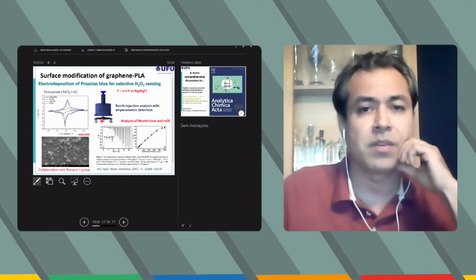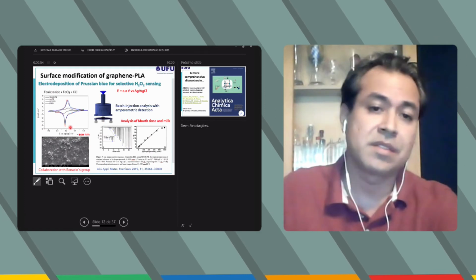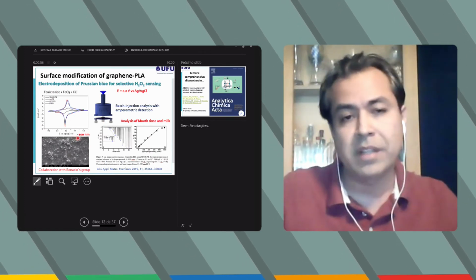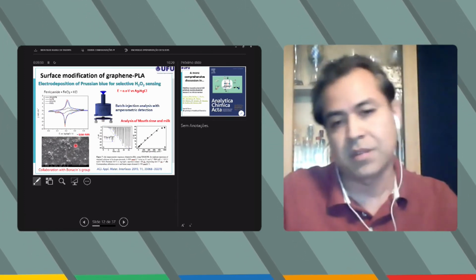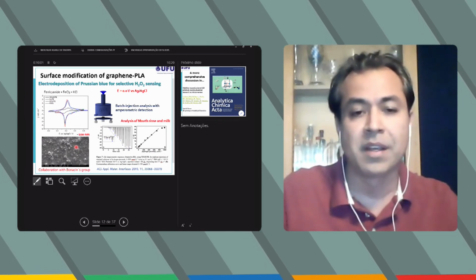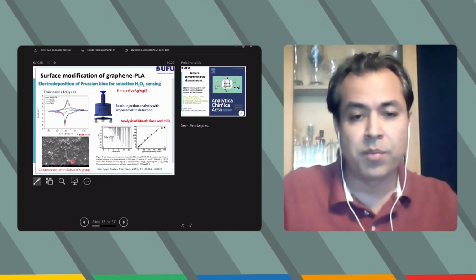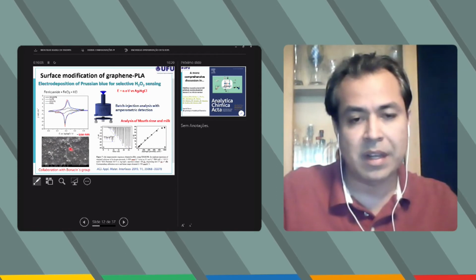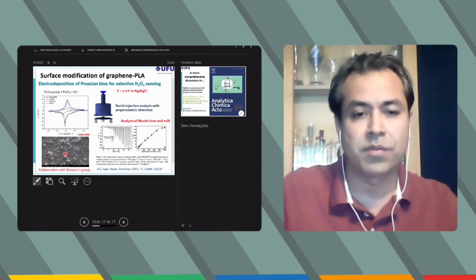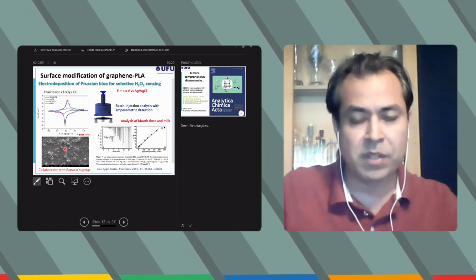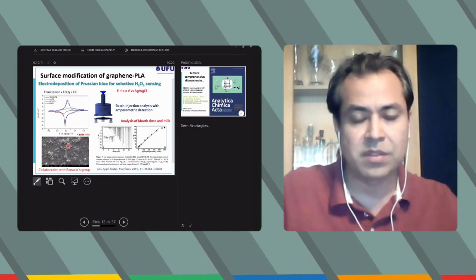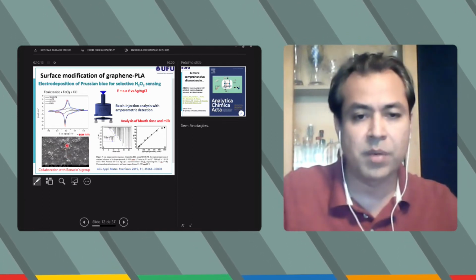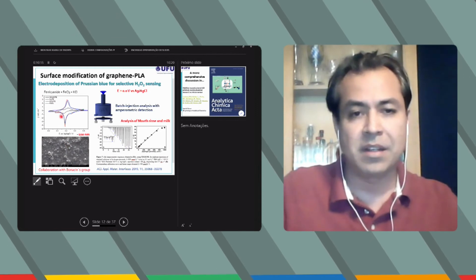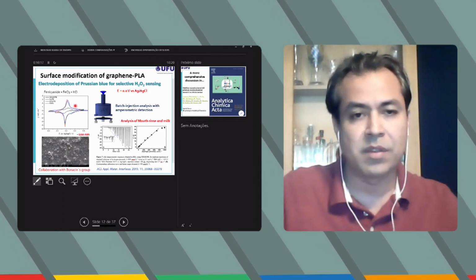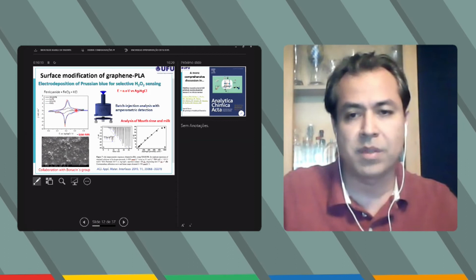Another possibility we also demonstrated in the group, instead of incorporating the catalyst inside the filament for the 3D printing, is the possibility to incorporate the modifiers or the catalyst over the 3D printed surface. So here you can see some pictures of typical structures of Prussian blue over the 3D printed electrode. Here you can see some comparison of the 3D printed surface with other conventional materials.